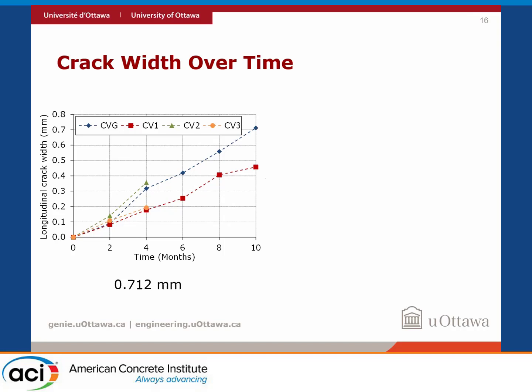So here is the longitudinal crack width for the type CV columns versus time. And we see that the specimen that had the highest crack width at the end of the testing period was the one that had the entire cage corroded. But early on, they all follow the same trend of growth of crack width with respect to time.